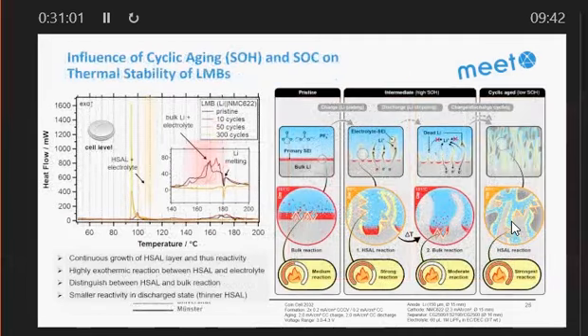Then what is the SOC thing? It's also very clear. At the beginning, pristine, the safety response is basically 180 degrees C because before there is no high surface area lithium, and then you discharge. In the discharge state, you dissolve some of the created high surface area lithium. That means you have less reactivity than in the charge state. And of course, with higher cycle number, you increase the amount of high surface area lithium and have more problems here.